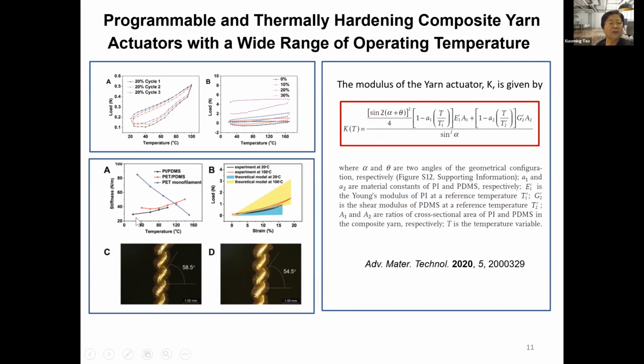And this diagram shows this blue line on the top. When temperature increases, the modulus actually increases and the stiffness increases. And that can give you more actuation power instead of softening. And this leads to applications such as a massaging fiber, because when temperature gets higher and you apply electricity to it, instead of becoming softened and reducing the reactive force, the force actually increases. We're trying to find out the mechanism and set up a mechanical model for this analysis, and that gives us a pretty reasonable prediction of the area where this actuation hardening occurs.